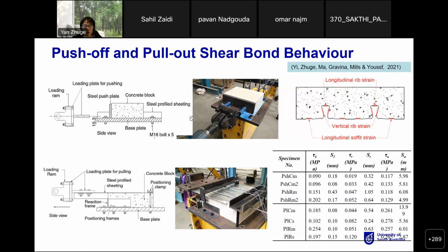So before the full scale testing, we did all this testing with two different methods, and both push off and pull out tests have been done by us, and the results were compared. So tau 1 in this form, as I said before, is the maximum chemical bond. You can see CRC got higher results. That's normal concrete, and that's crumb rubber concrete. You can see that for the crumb rubber concrete, the chemical bond tau 1 is much higher compared to the normal concrete. Okay.